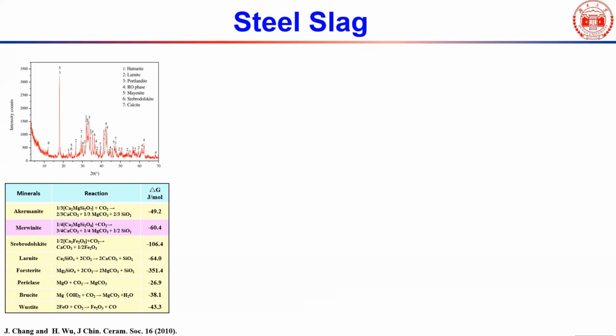The other exception actually is steel slag. Steel slag is not what we call a glassy slag, because it is not water quenched or fast cooled. Usually they cool it by pouring the slag onto the ground, or now some Chinese companies developed a process: pour it into a big steel pan and let it cool slowly, then spray some water on. Then the big chunks break into small pieces, right?